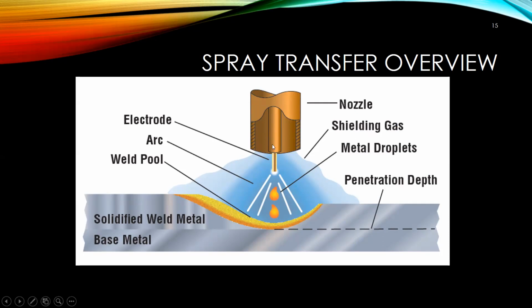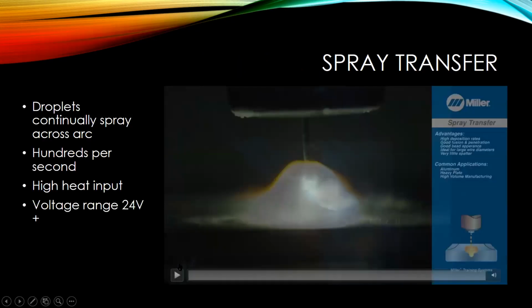So we have our nozzle here, contact tip inside, wire coming out of the contact tip, our electrode. And so we have our arc. We have our shielding gas that's protecting our arc and our molten puddle from any oxygen or anything that might contaminate the puddle. And as you'll see, there's a pretty good distance between the end of the wire and the puddle itself. And what's happening is little droplets of metal are being pinched off and thrown across that arc into that molten puddle. And typically there's hundreds per second.